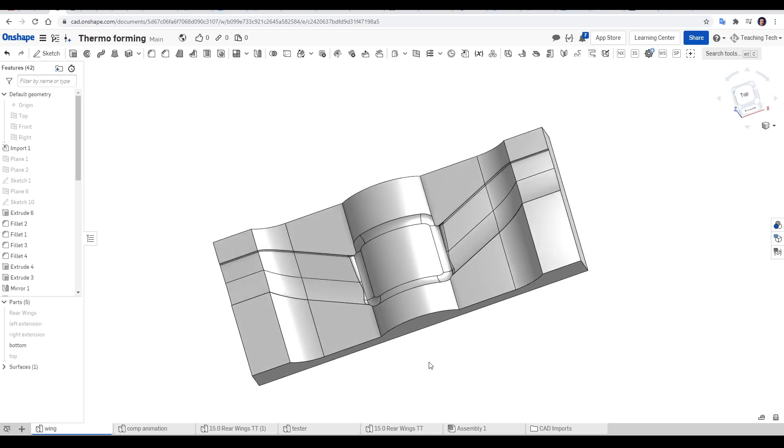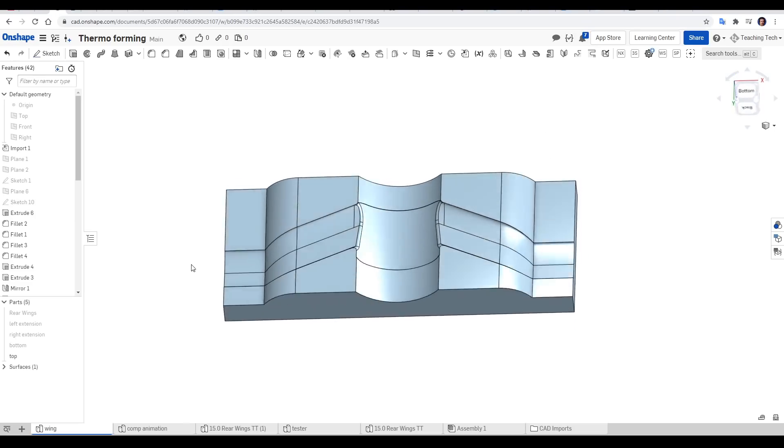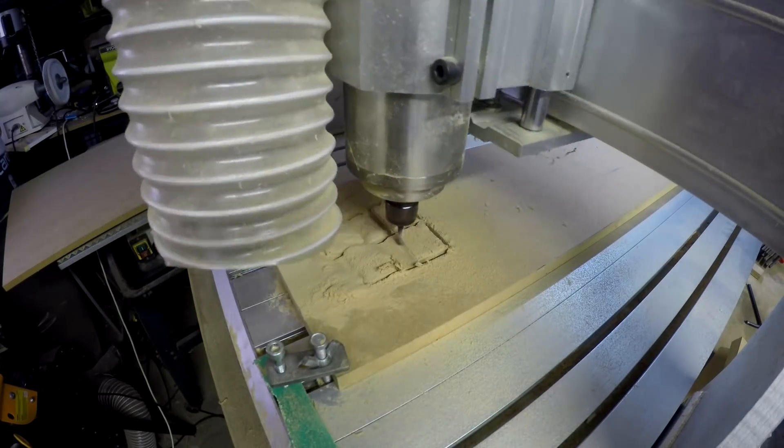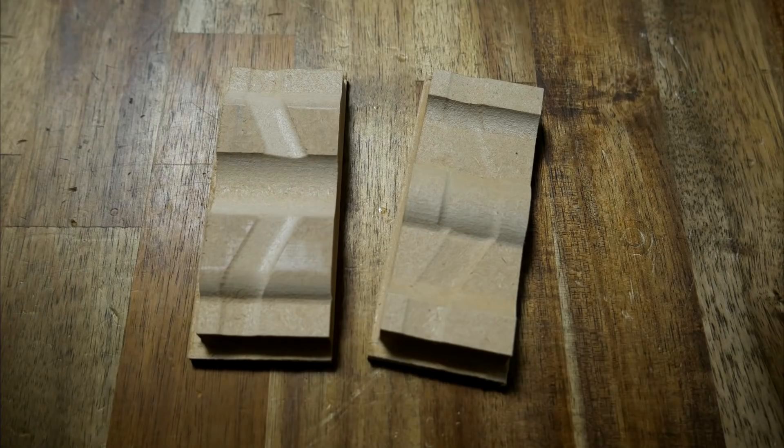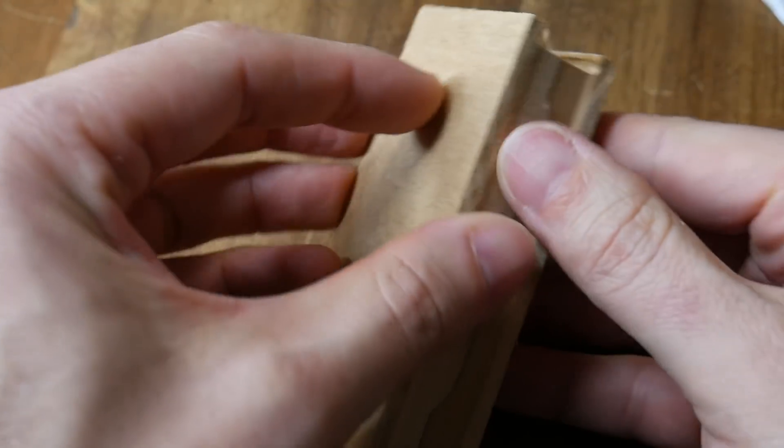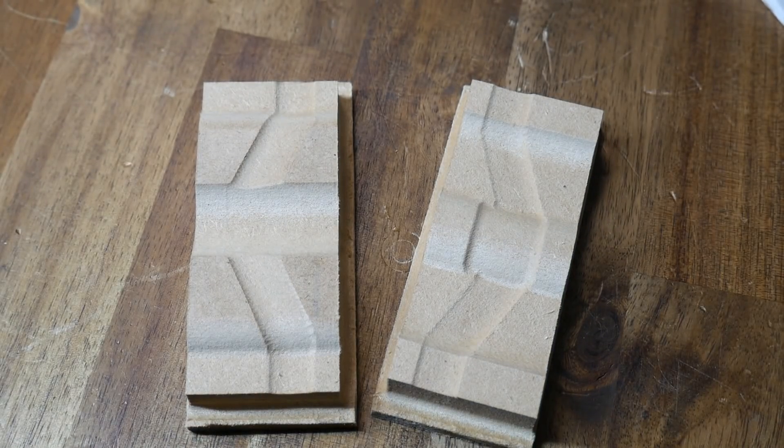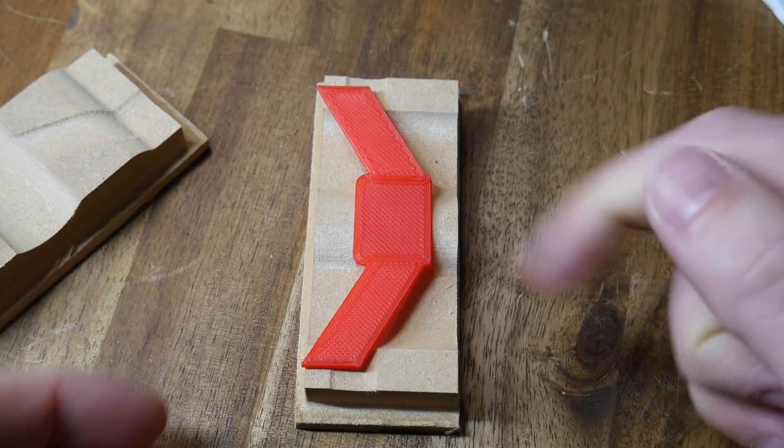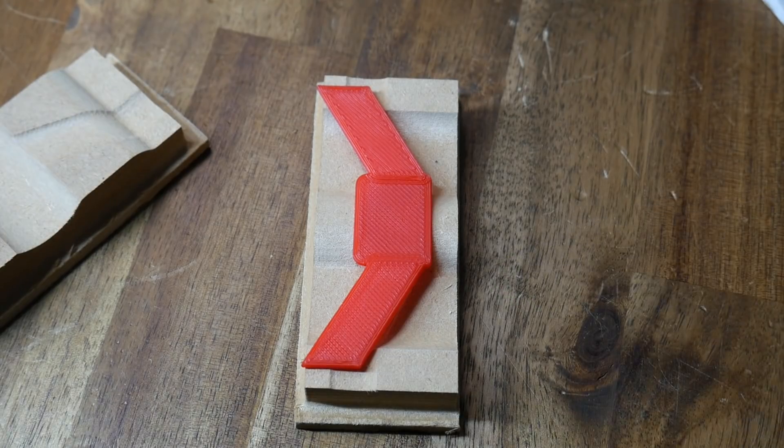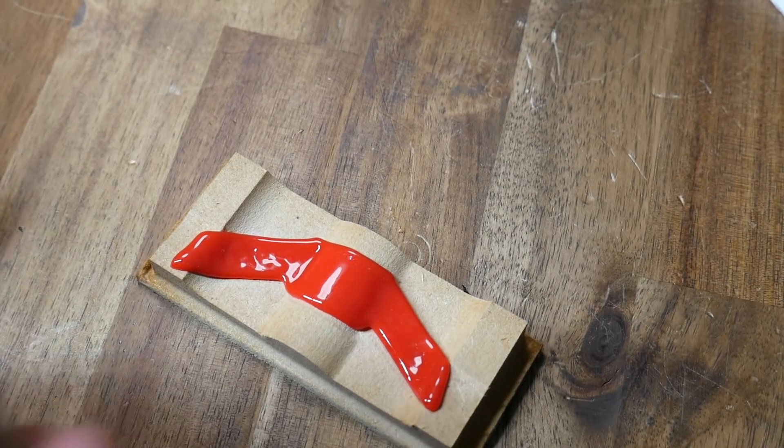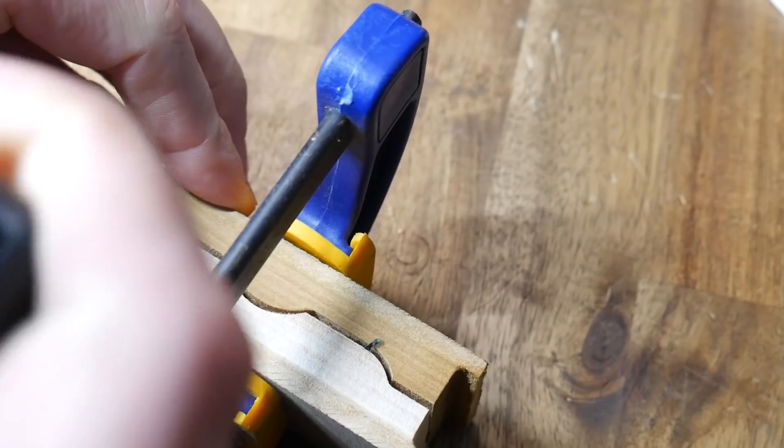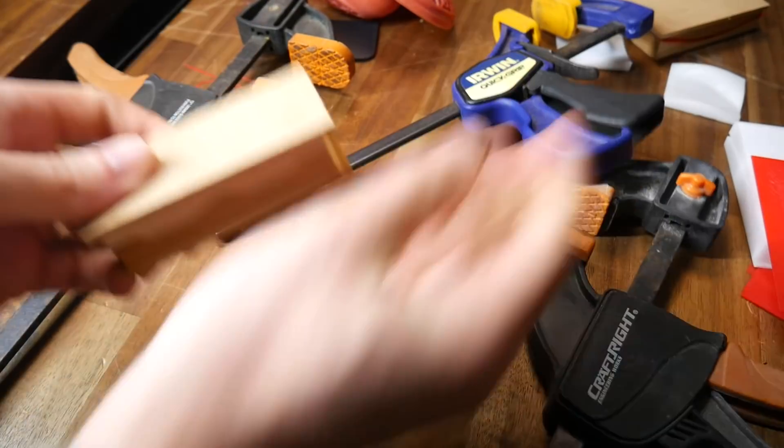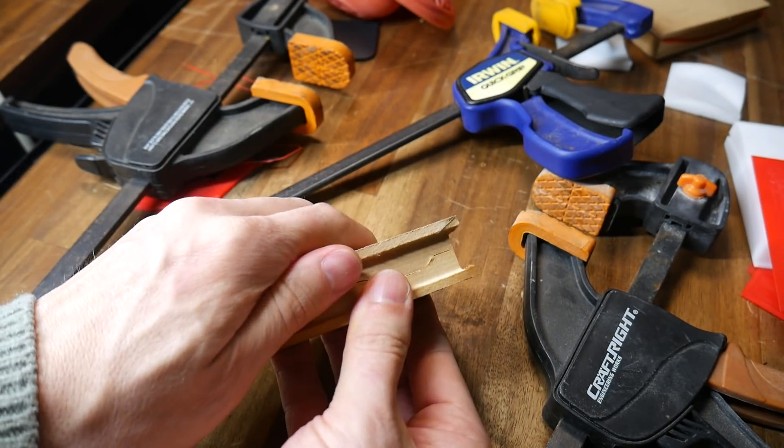Using the team's prototype rear wing, I again designed a two-part mold, extending the edges to let air and excess plastic escape. Like with thermoforming, I chose MDF to machine the two halves of the mold, and without any post-processing they both turned out quite clean. Of prime importance is the fact that the two halves mate together nicely. For compression molding we don't use a flat sheet but instead use a slug, and I designed this one in CAD. The outer tip doesn't quite match, but the rest should be pretty close. The slug was placed on one half of the mold and the whole lot put into the oven. In this case we need the temperature to be high enough that the plastic really starts to melt. After that, we can put the mold together and apply some clamps to push everything into position.